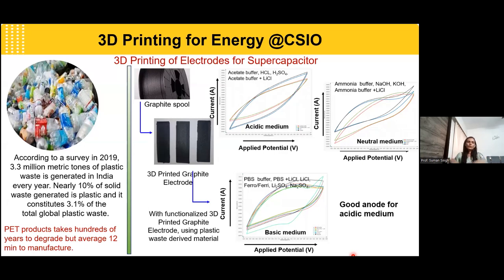The previous slide showed unfunctionalized graphite electrodes, where bare electrodes were used. And in this case, these were functionalized with the activated carbon, which we have derived from this waste material. So there we wanted two things: less energy consumption, and at the same time a solution to this plastic waste.